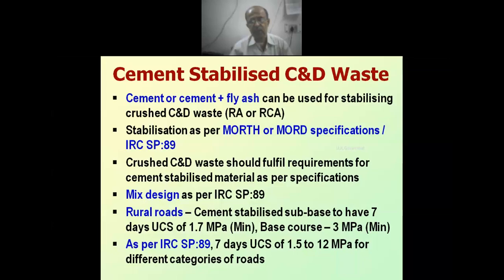For higher category roads, whatever the material strength is, the stabilized material strength normally should not be below 4.5 MPa. That's what we usually say. So 4.5 MPa to 12 MPa. 12 MPa is a little bit higher.